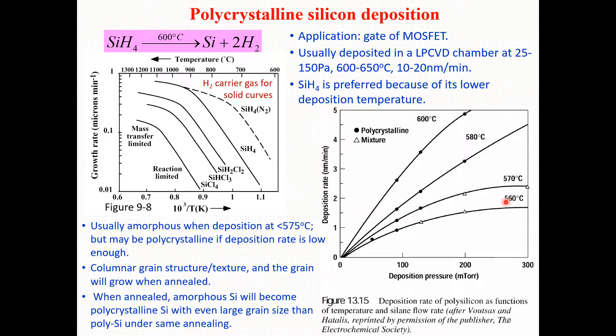When we have a lower temperature — around 560 degrees centigrade — we can have mixtures of polycrystalline and amorphous silicon. We usually get amorphous silicon when the deposition takes place at a temperature smaller than 575 degrees centigrade. That is why we show it here at 560 and 570 degrees centigrade — when the temperature is smaller than 575°C, we get amorphous silicon deposited.